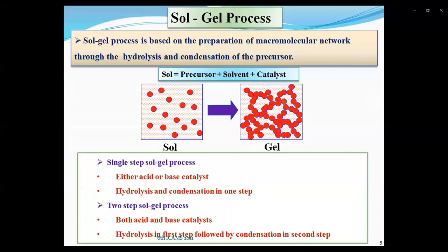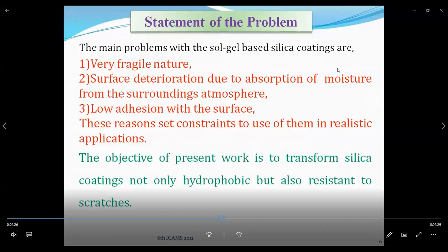Statement of the problem. The main problems with the sol-gel based silica coatings are, first, they are very fragile in nature. Second, surface deterioration due to absorption of moisture from the surrounding atmosphere, and low adhesion with the surface. These constraints limit their use in realistic applications. The objective of the present work is to transform silica coating not only into hydrophobic but also resistant to scratches.